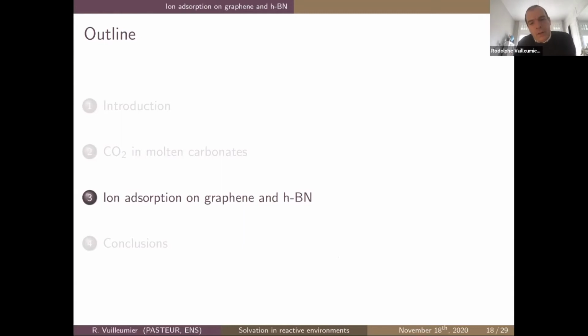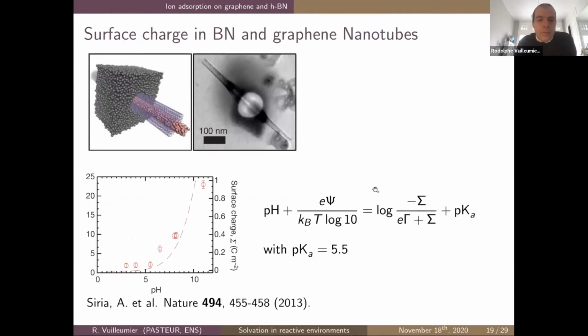And the adsorption of hydroxide on graphene and hBN. There I relate to experiments that were conducted by Lydéric Bocquet, who showed that again at the nanoscale, we've heard some of these experiments by Laura this morning, and more later with Mathieu. The experiment at this nanoscale looked at the transport of current through nanotubes of BN or graphene, and Lydéric showed that there were quite large surface charges, especially on the boron nitride, that can reach up to 1 coulomb per square meter. We call them giant charges.